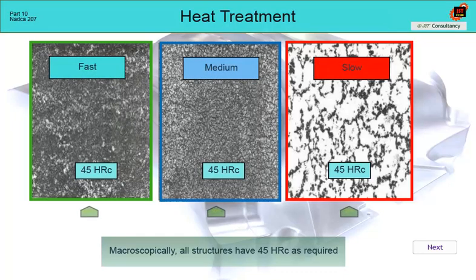What does this mean? The tool shop simply does not know how the hardening actually turned out. It does not have the equipment and does not perform metallographic evaluation. For this reason, testing according to NADCA 207 is important. For the tool shop, it is usually the only way to verify the quality of the heat treatment. Otherwise, the fact that the structure was faulty after hardening will only be apparent to the customer by a part breaking or a low service life.